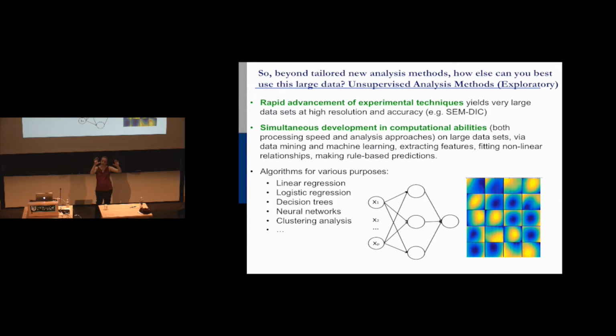And then you also have, at each point, like 100 microstructural variables. So you can imagine, how close are you to a grain boundary? Are you in a really big grain or a really small grain? How misoriented is the grain next to you? If I'm on the surface and I'm looking underneath me, do I have a bunch of small grains? Do I have a really big grain? What's going on subsurface? And so each of these hundreds of millions of data points has an estimate of the damage map, but also has 100 to 200 microstructural variables that explain the microstructure surrounding you.